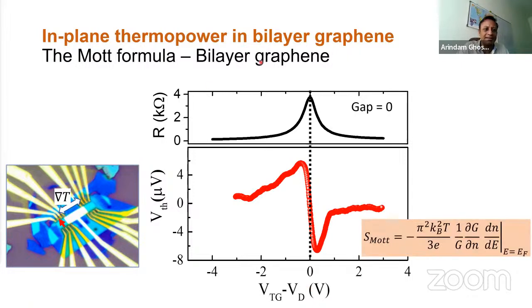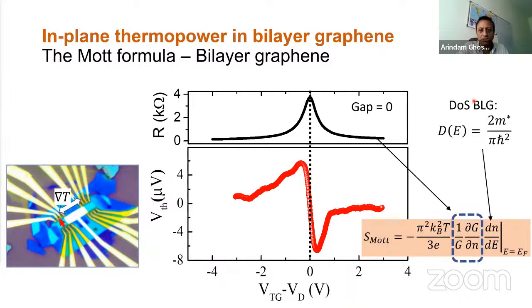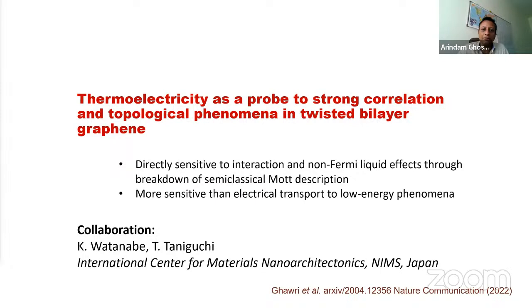This work was done with bilayer graphene, and bilayer graphene has a density of states which is constant, like a standard metal. If I multiply the derivative of this conductance, which is here, with the constant density of states, you can beautifully reproduce the experimental thermal voltage, which essentially tells us that bilayer graphene is a good quality semi-classical metal, and we don't have to worry too much about strong physics. I want to show you what happens when I use, instead of conventional graphene, a twisted bilayer graphene. And that's where the fun starts happening.